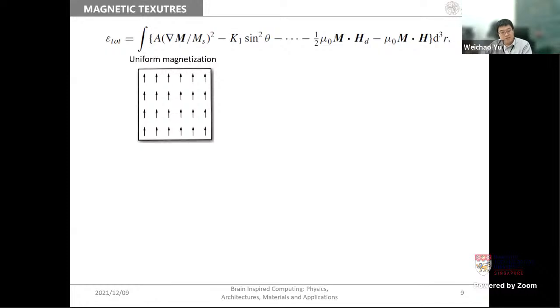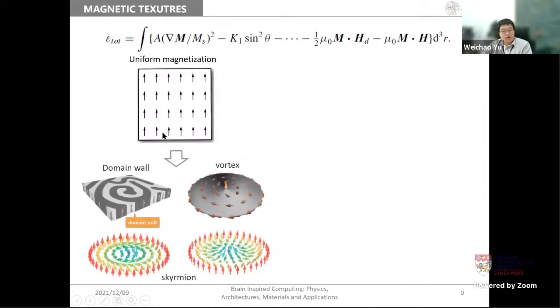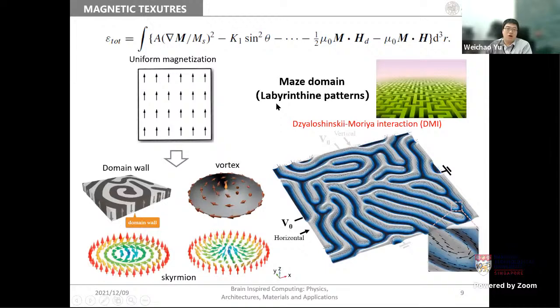In magnetic systems, we have varieties of interactions such as exchange, anisotropy, demagnetizing field, and Zeeman field, etc. In order to minimize the energy, the ground state is no longer uniform. There will be magnetic textures such as domain walls, vortex, skyrmions, etc. Our interest today is the maze domain, so-called labyrinthine patterns, which is stabilized by the chiral Dzyaloshinskii-Moriya interaction, DMI. Here, the white and black color represents the out-of-plane magnetization, and the arrows are for the in-plane components.